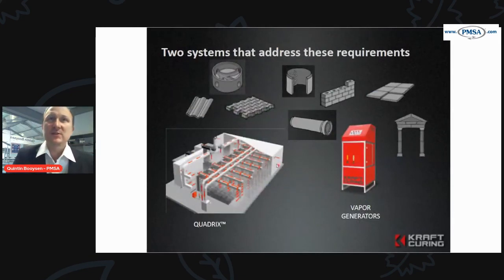Methods that we can use is the closed room method, which I spoke of a little bit earlier. So we have a room with good circulation, we insulate it fully, and we call it a Quadrix system, where we're controlling the moisture, we're controlling the heat, we're controlling the circulation, and ultimately at the end, we also control the exhausting of the system. When we finish with the curing, we can exhaust it quickly so that we don't end up with water condensating inside of our curing rooms. So that's a Quadrix system that we talk of.